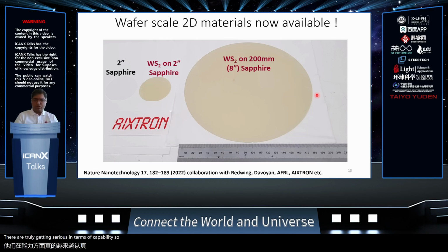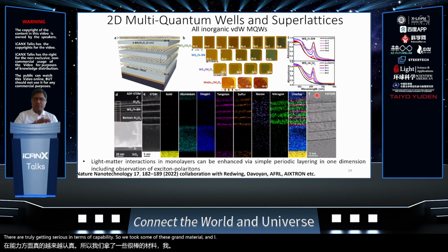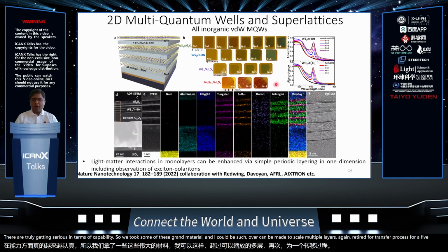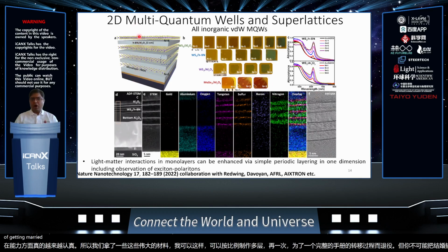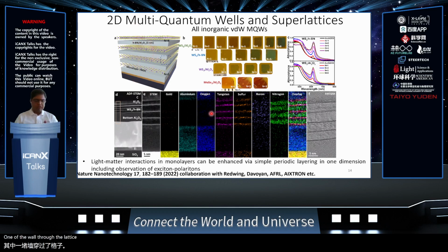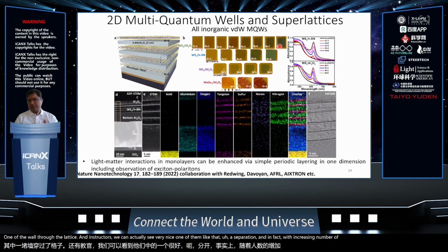So we took some of this grown material and actually stacked over centimeter scale multiple layers, with hand. This is all a transfer process, so it's all manual, but you can automate it to make this kind of artificially made van der Waals superlattice. And in these structures, you can actually see very nice quantum well-like separation. With increasing number of n, you can see much larger and larger absorption approaching near unity levels over here in the exciton.